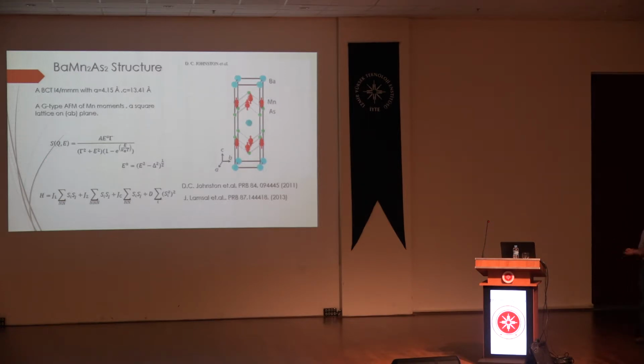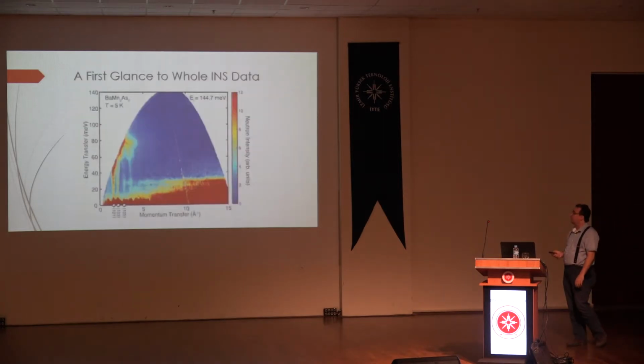What are they going to give me? The gamma value gives me the Hall effect results. If I introduce a hole into the Fermi surface of this material, there will be more carriers in the system. That means the damping oscillator damps the spin waves more. So gamma needs to be increased, and the spin wave needs to be smeared and disappear. This is the idea behind using the second way.